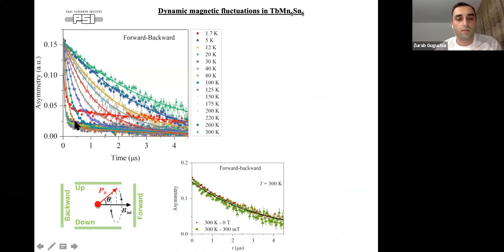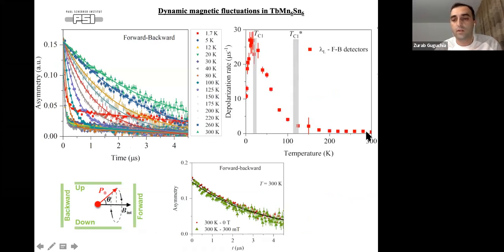If you follow the relaxation rate of this dynamic signal as a function of temperature, it means that you have some kind of magnetic fluctuation, some dynamics, involved in this magnetic ordering. The relaxation rate is more or less constant, but then below 120 Kelvin it increases. This is a slowing down of these slow magnetic fluctuations. And then below 25 Kelvin, we see a strong reduction, and the amplitude of the signal also starts to reduce below this temperature. This is the temperature below which we also see the additional frequency. So it seems that the fluctuations become static enough that in muSR we detect coherent precession, and then we enter the static regime.